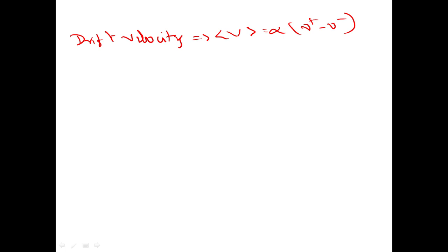Here the drift velocity comes into existence: alpha into nu plus minus nu minus. So if the drift velocity is present, there is some velocity with which the atoms are moving. Hence, there is a contribution of a Fickian term and the drift term to the diffusion flux.